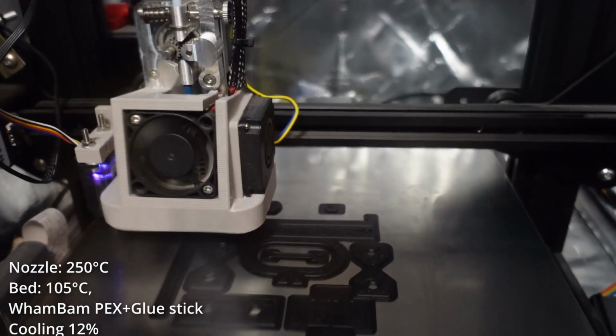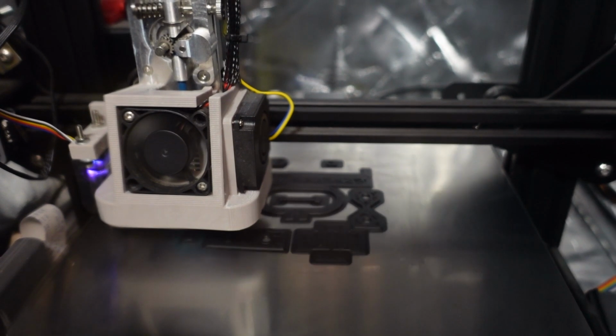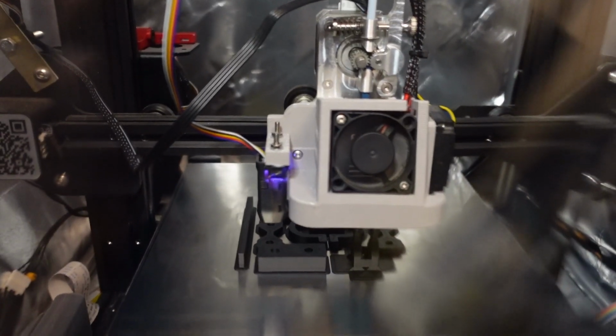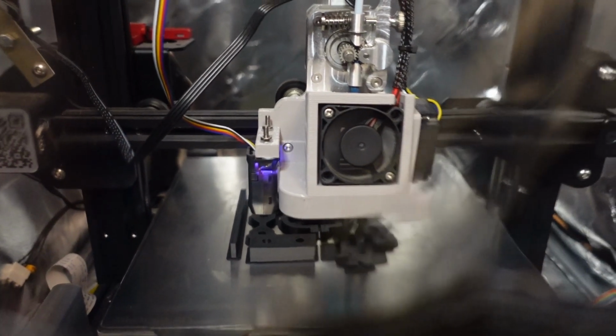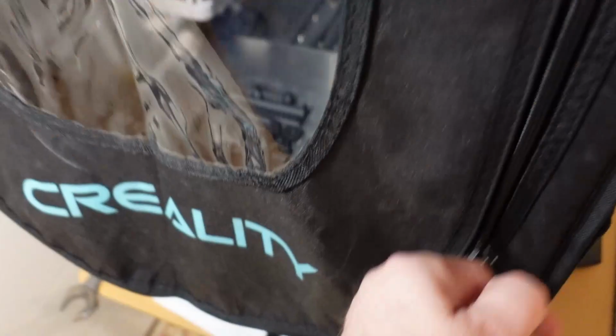So all test specimens will be printed on 250 degrees Celsius, bed temperature 105 degrees Celsius, and I'm using a Wham Bam PEX with the glue stick, and cooling is 12%. And the printing is finished in almost 5 hours, and the temperature inside the enclosure was 47 Celsius.